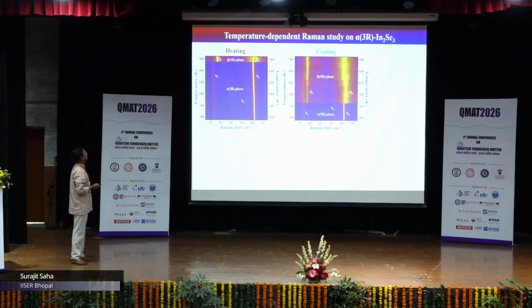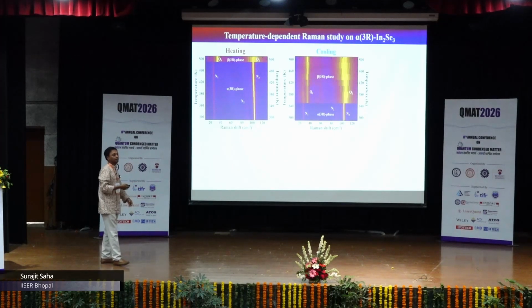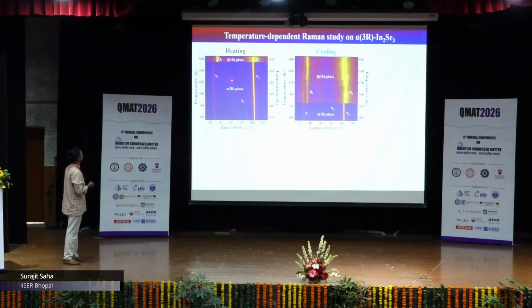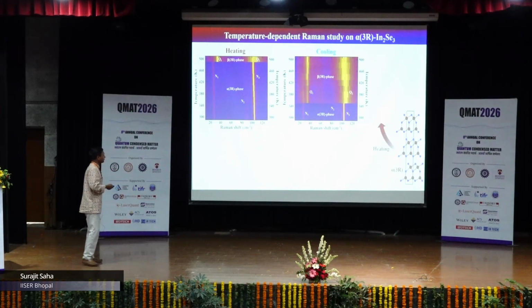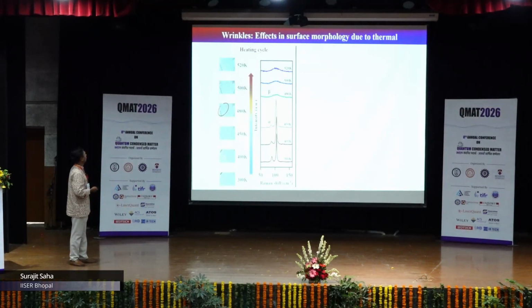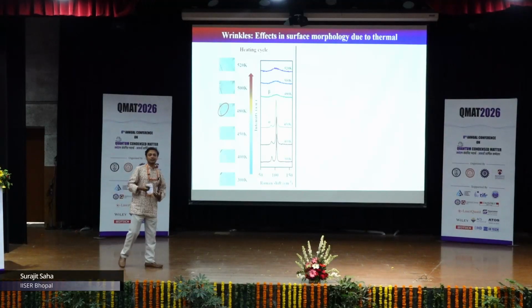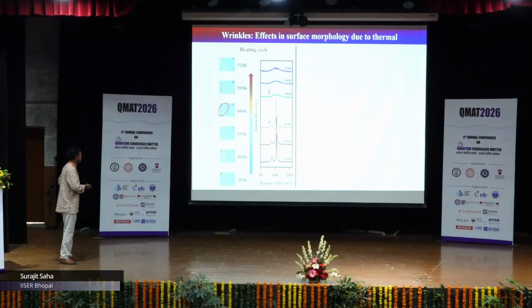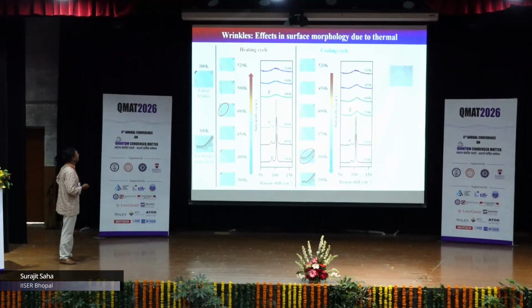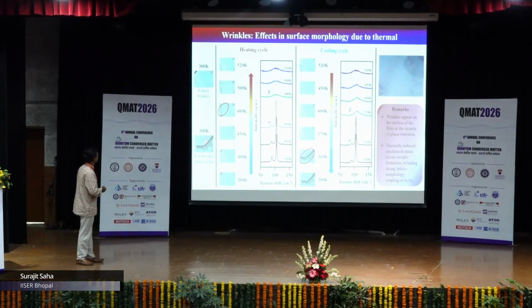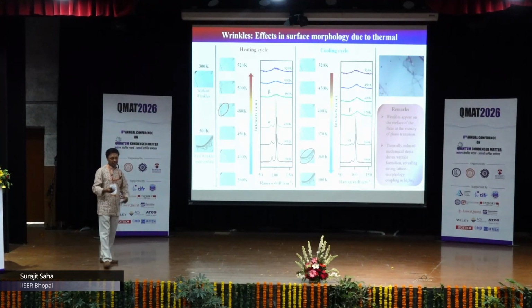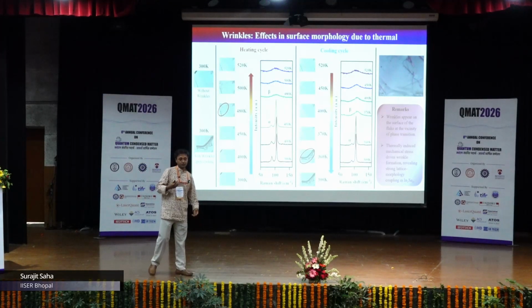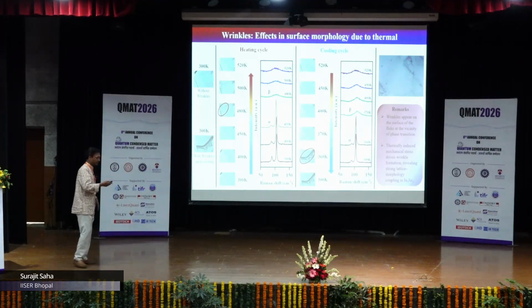So now, again, this is looking at how the alpha 3R phase behaves in this thermal cycle. The alpha 3R phase individually also shows a reversible transition, with a much fatter hysteretic loop. Another interesting part of this is that a wrinkle gets formed as we do this thermal cycle, and here you can see the wrinkles developing. I think I have a video as well. So from this video, one can see, this is the starting picture, which is very clean. And then as it goes through the thermal cycle, it forms the wrinkles. So it's not only that the structural transition is happening, there is also strain that generates, and it leads to the formation of wrinkles in the structures.